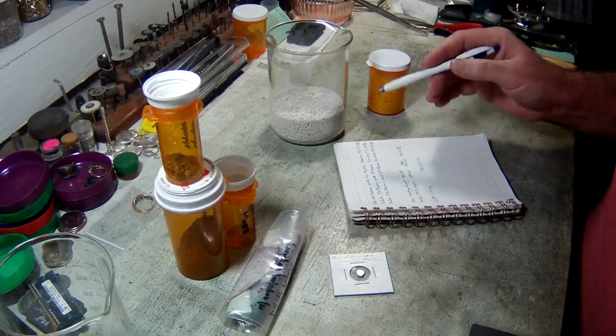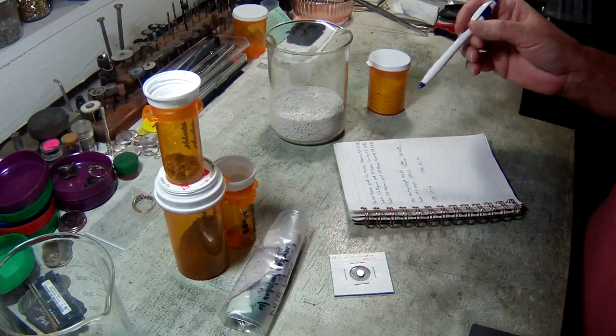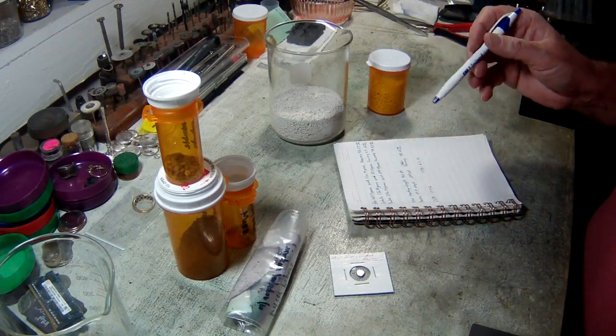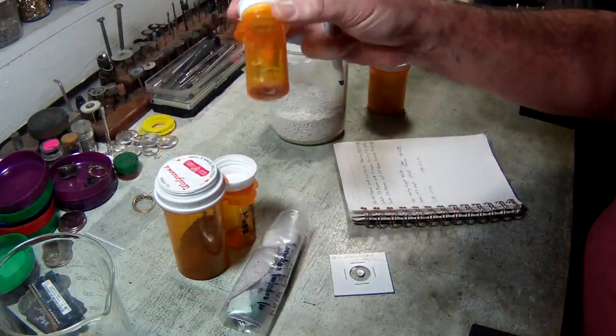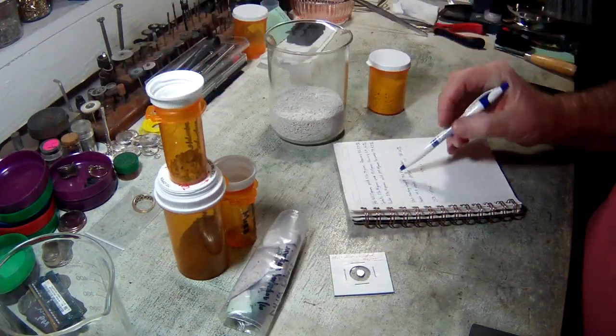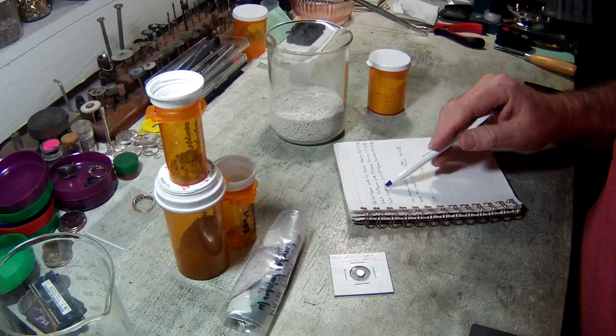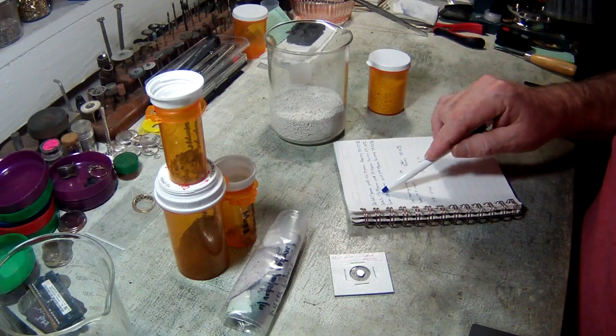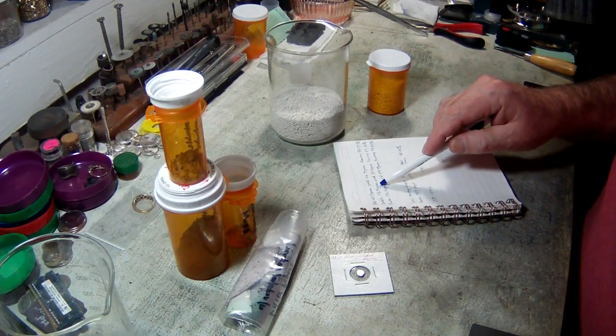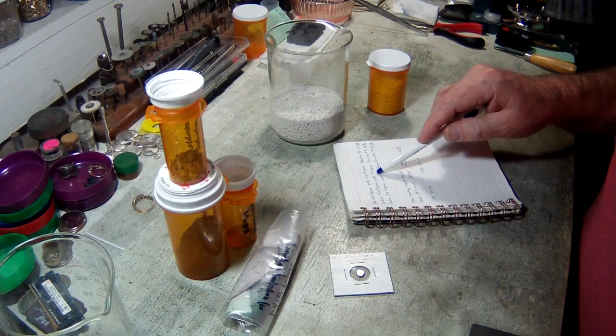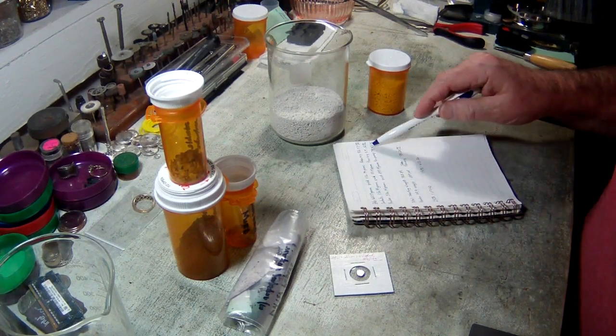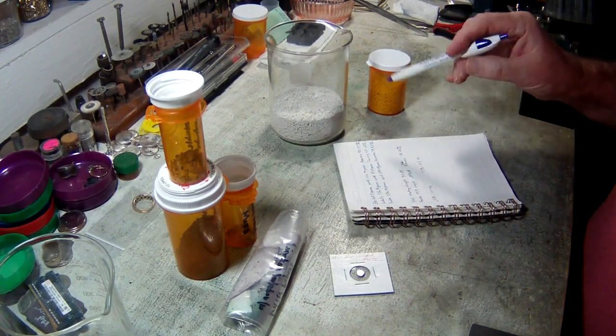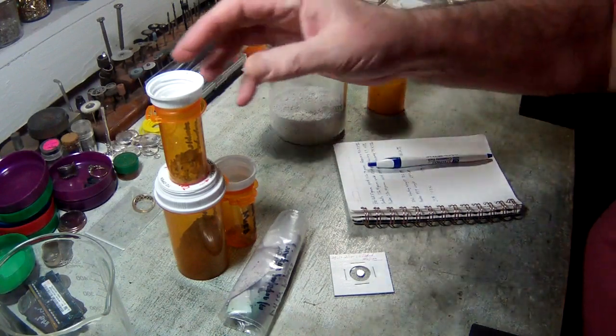The contacts were our worst, which I figured because of the copper and other materials and this non-dissolvable material. I knew they were going to be kind of a 50-50 yield. We actually had 156.98 grams. We yielded 93.45 grams, which is a 59.52% yield, which is about right.